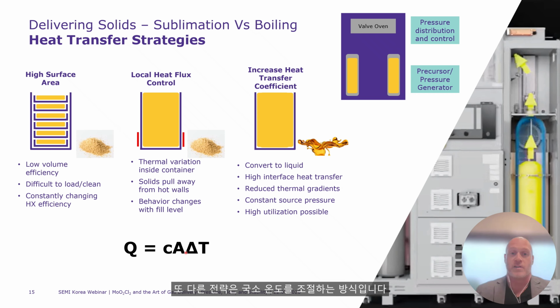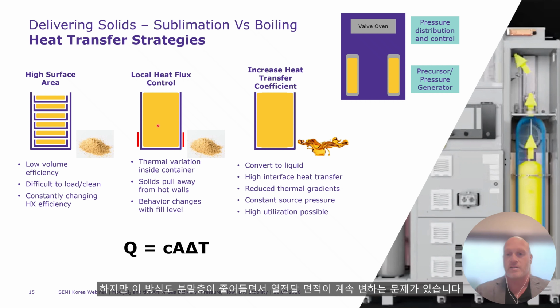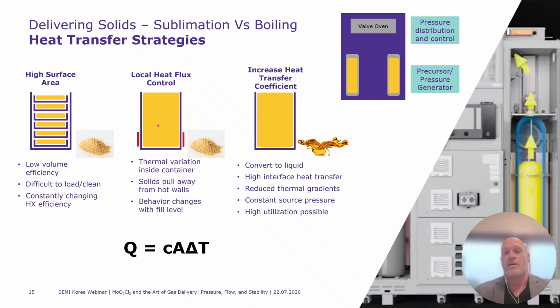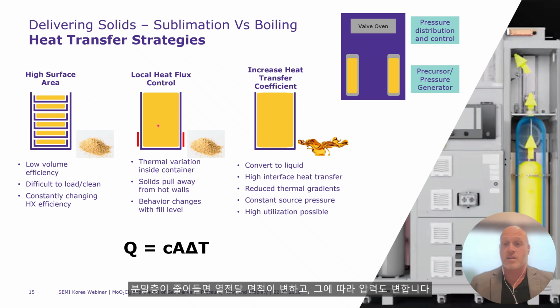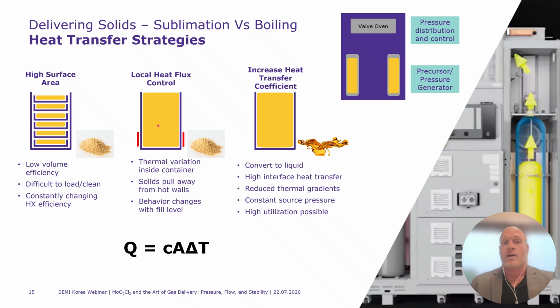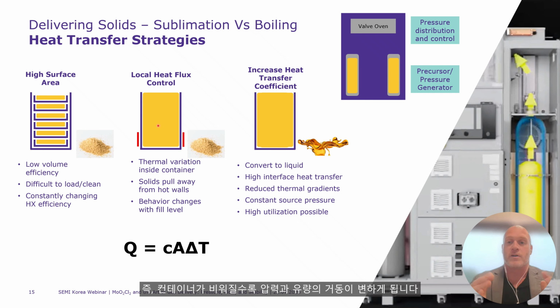A different strategy is trying to adjust your local temperature. You can insert a heater into the container to really drive up that temperature. As the powder bed drops, your powder is going into here. This center cartoon is really around local heat flux control, so you're driving heat into where the powder is going to go. But part of the issue here is, again, your heat transfer area is adjusting as you're depleting the powder bed. As that happens, your delivery pressure changes. So the behavior of your pressure and flow is going to change as you deplete your vessel.